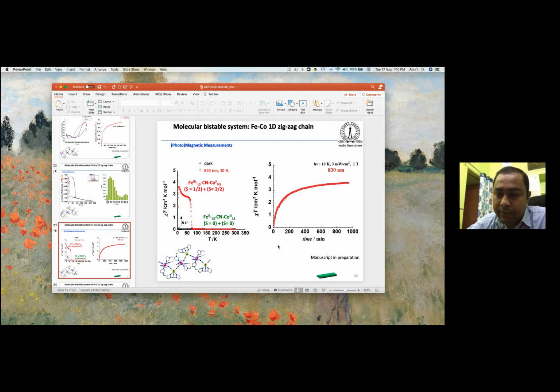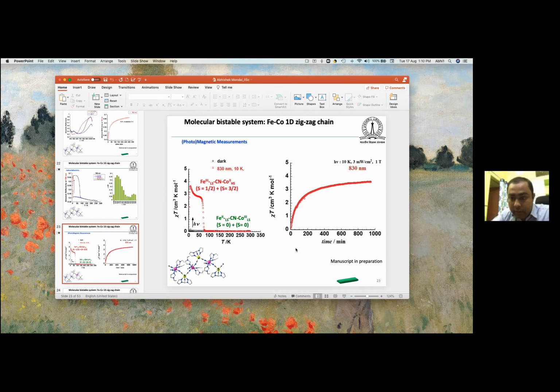One thing we have observed is that you have to keep some distance between your sample and the laser tip. When you increase or decrease this distance between the laser light and the sample, there is an effect. Sometimes when you use high power light, we can see the photo conversion effectively, or even in less time. But again, there is another problem. If you use high power, you cannot stabilize the temperature, because you are at this 10 Kelvin temperature. There is local heating also, which plays a very important role.